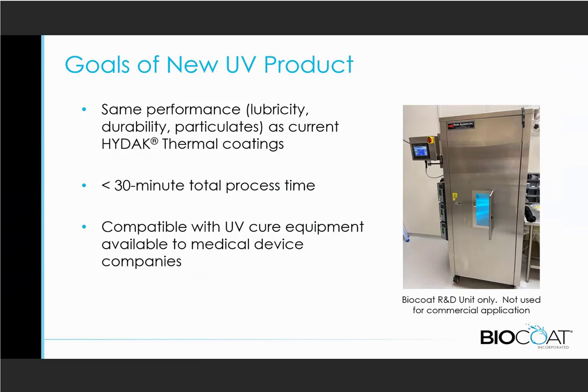One of the issues with a thermal cure system is that it takes a little longer to cure. So we wanted to reduce the process time to less than 30 minutes, from the coating through the curing, that entire process. As I said, the thermal system can take a little bit longer than that. We also wanted to ensure compatibility with UV cure equipment that is available, or sometimes even already installed at some medical device companies, so that people can rest assured that what we're developing doesn't change the investment they've already made in their coating equipment. That's being done by these UV flood lamps, which you can see on our prototype coating system here.